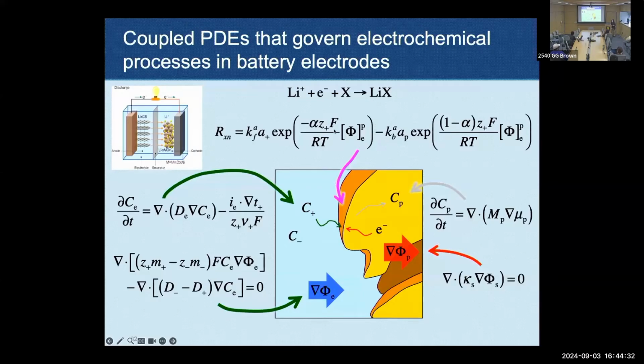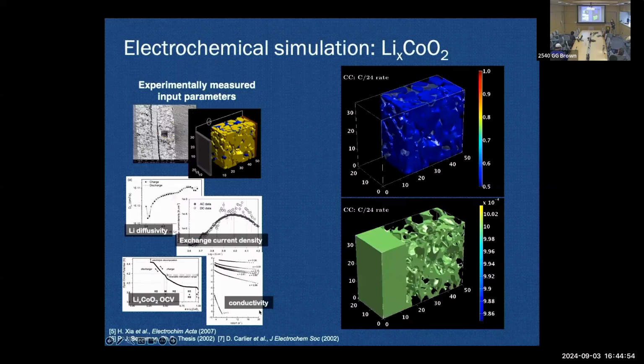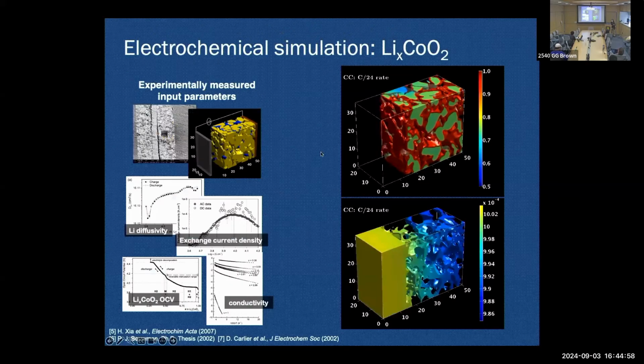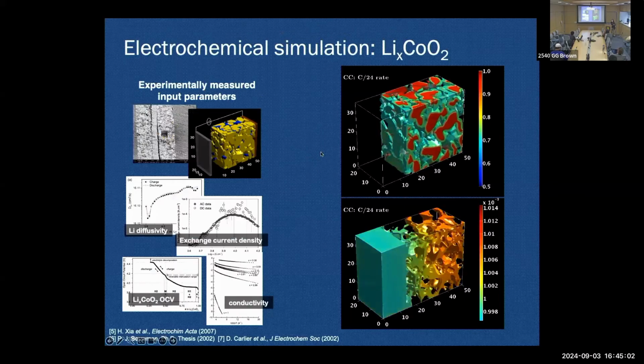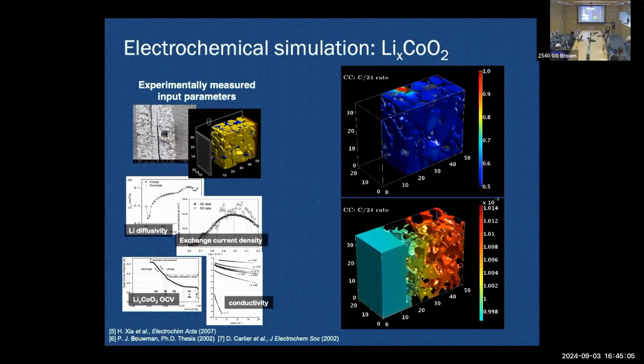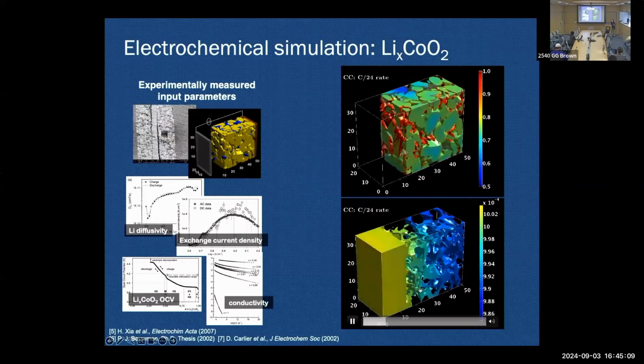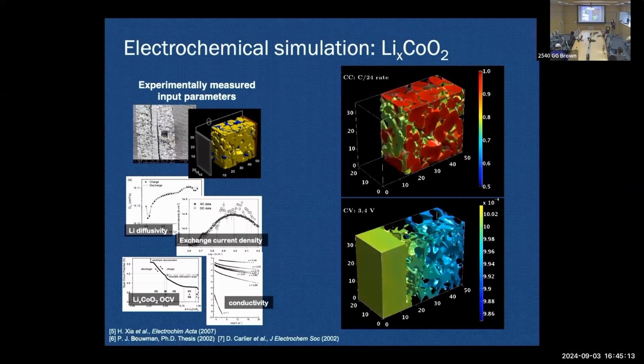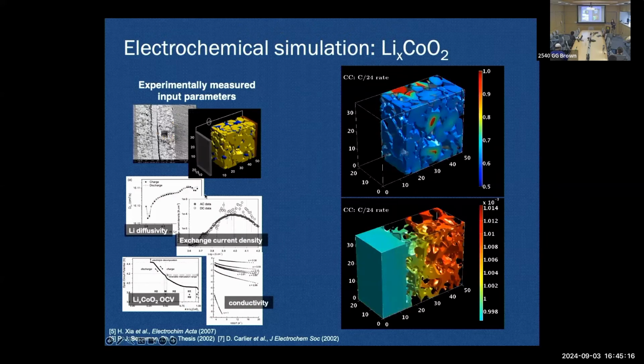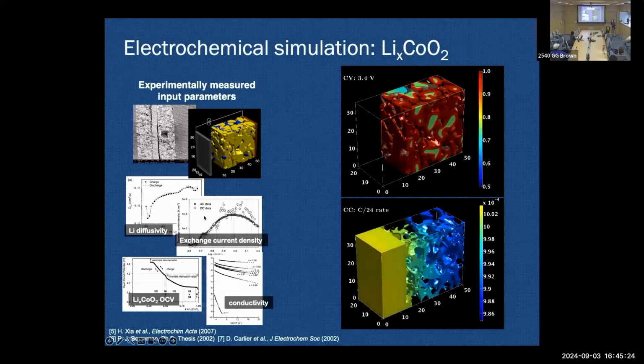The solution of that gives you concentration and also electrostatic potential. That goes into this equation that gives you the reaction rate. You calculate the reaction rate, and that sets the boundary condition here. Then you solve all the equations. In this region, you solve this equation, and in this region, you solve this equation. When you do that, you get results like this. The top is the lithium content in lithium cobalt oxide during lithiation and delithiation, and the bottom is the concentration of lithium ion in the electrolyte phase. Those are parameterized with various literature values for the OCV, diffusivity, conductivity, etc.